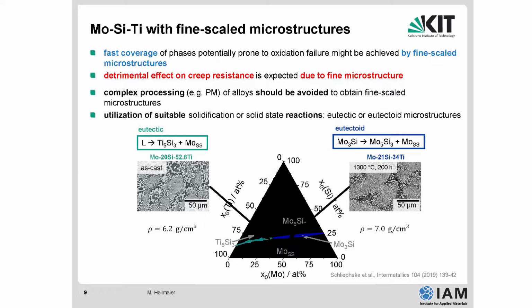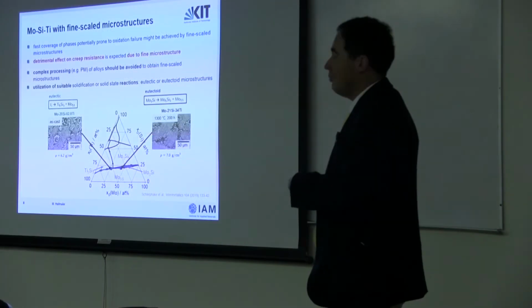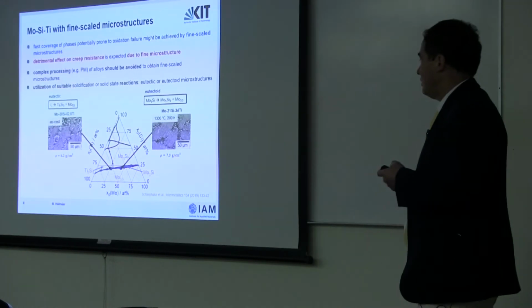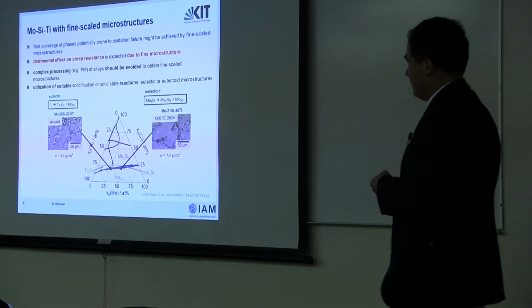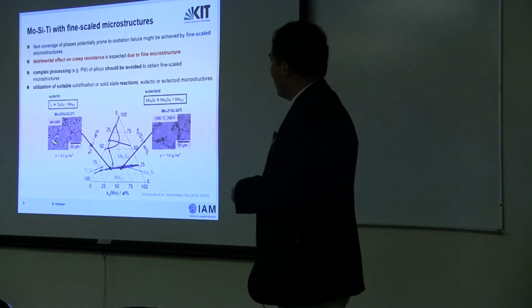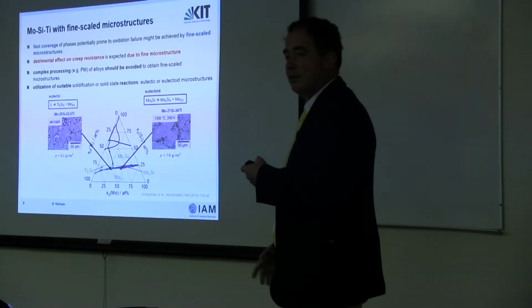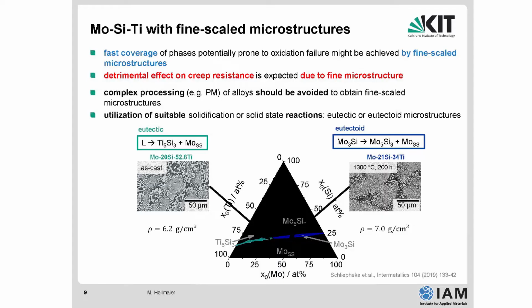This points already to the fact that we have a much more stable microstructure in these molybdenum-based alloys than in the previously shown nickel-based superalloys. At 1300 degrees Celsius, the nickel-based superalloy is nearly about to melt, right? So here you need this for this long time to form the thermodynamically stable microstructure. Okay. And you can do it by casting. So this is all cast alloys, nothing special, no powder metallurgy, nothing.